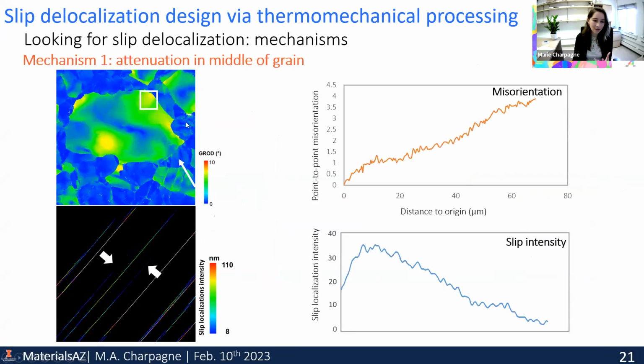And looking at how this happens, really, I just want to detail a few mechanisms really quick. We have identified essentially 4 mechanisms by which slip delocalization happens, like the disappearance of these very intense slip bands. The first one is directly related to the presence of lattice rotations. And here we just take a snapshot of one of those larger grains where you see we have a hotspot of lattice rotations.